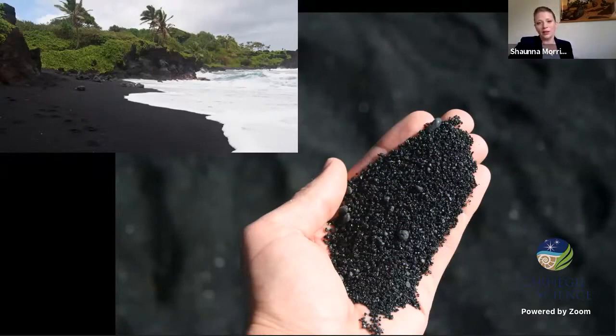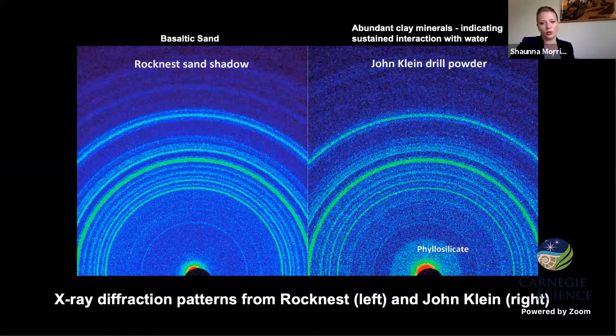That's not Mars. But the major difference between the two is the phyllosilicate or clay mineral band we're seeing near the bottom of the pattern. What we're seeing here is the first definitive proof of a long-standing body of water on Mars. This clay mineral formed as the result of olivine crystals sitting in water for a very long time. Not only do we know that there was water and that the parent material was olivine, but based on the type of clay mineral, we know that the water in Gale was fresh and it had a neutral pH. This is very promising as an environment that could have hosted life. It was a very comfortable, hospitable place that was not too harsh at all.